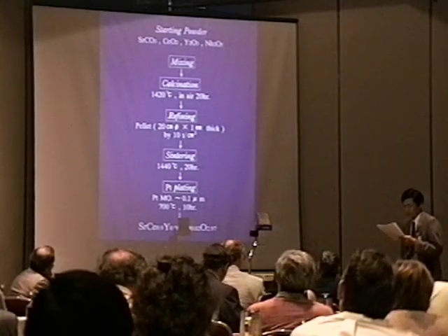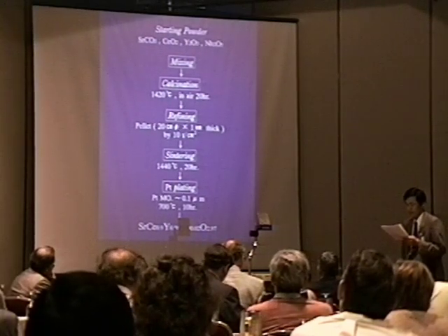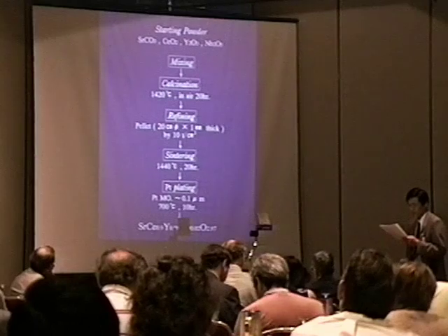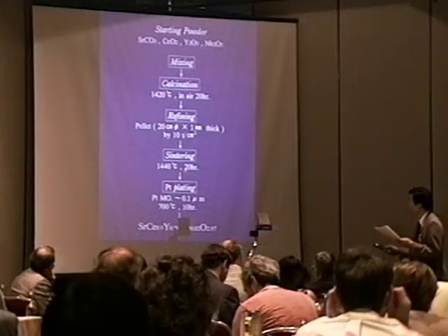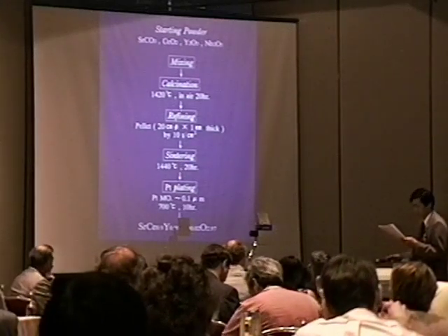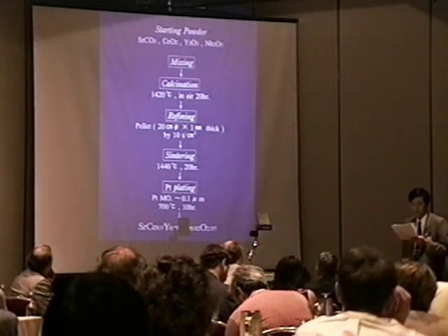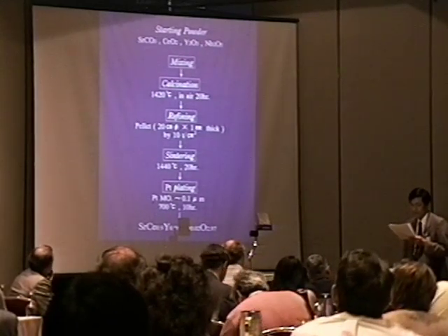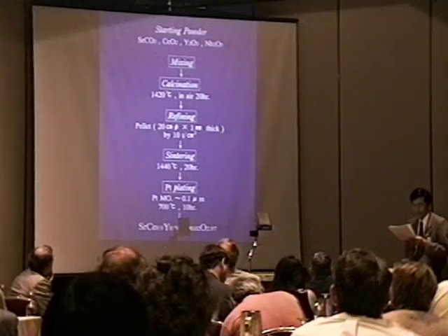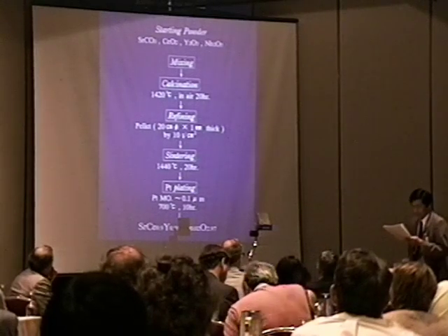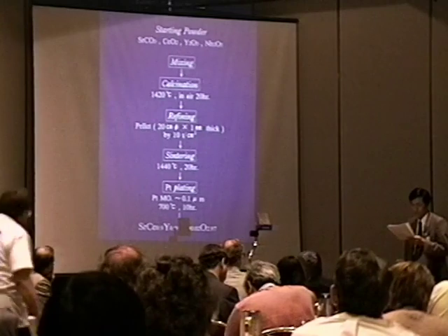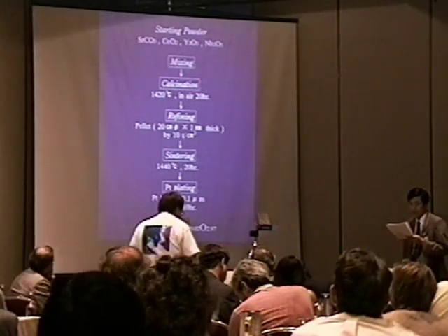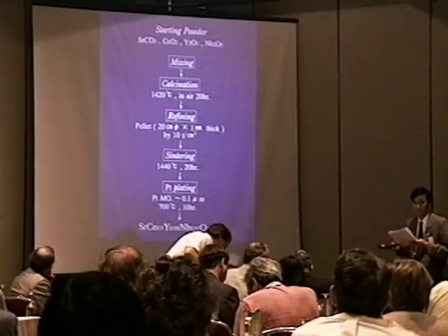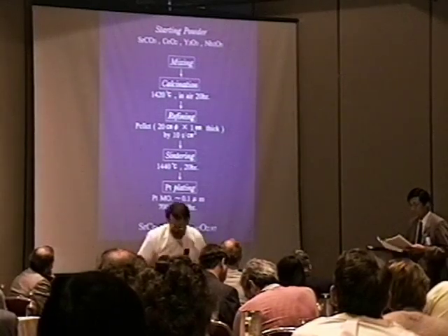And then these were sintered in a furnace at 1,440 degrees centigrade in air for 20 hours. After that, sample surfaces were painted with an organic platinum compound and baked at 700 degrees centigrade for 10 hours to obtain a porous platinum film on the sample. Next slide, please.